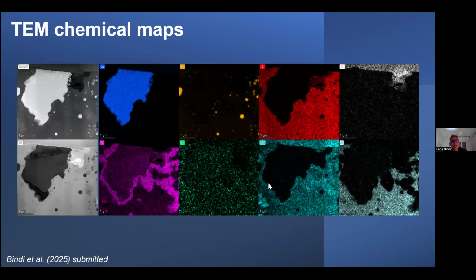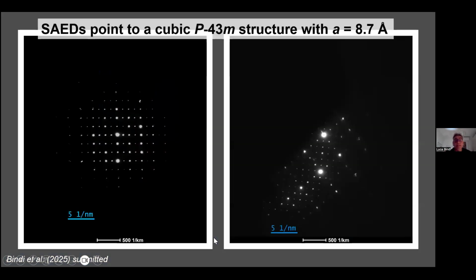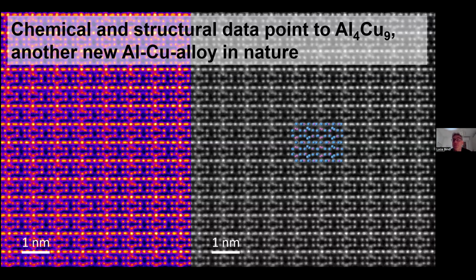And look at the chemical maps collected with a TEM. You can see here an enrichment of aluminum at the border, testifying the reactions we were discussing before. So the presence of an aluminum-rich oxygen-bearing phase, something like corundum or a new generation of spinel at the border, and the copper aluminum alloy, the metal inside here, which is actually pretty impressive. And again, look at the new phase. This is the selected area diffraction pattern of the new phase, indicating a cubic symmetry. And of course, by analogy with a synthetic counterpart, we were able to individuate, thanks to the EDS spots and this kind of information from a structural point of view, that it corresponds to this stoichiometry, Al4Cu9, which could be another new copper aluminum alloy.